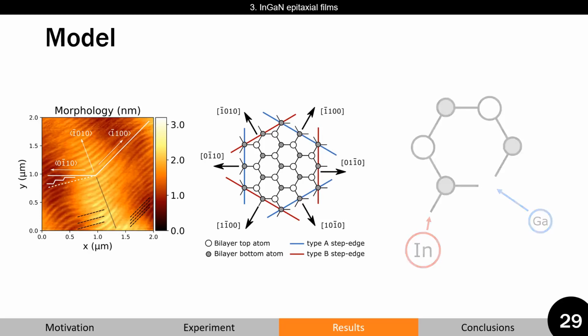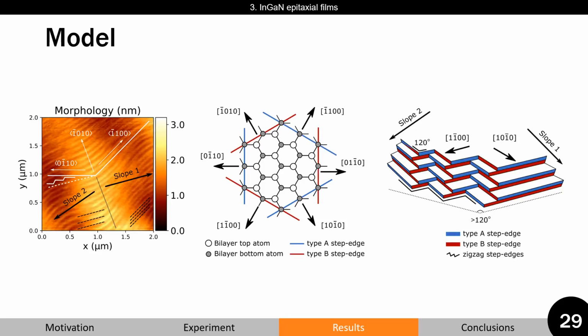Using this schematic illustration, we see that if metal ions land on slope 1, they can be incorporated only at type B edges, hence indium incorporation is preferred and an indium-rich slope is formed. For slope 2, where we see this deviation from crystallographic orientation due to zigzag structure, metal atoms can be incorporated on both type A and type B edges, hence an indium-poor slope is formed.